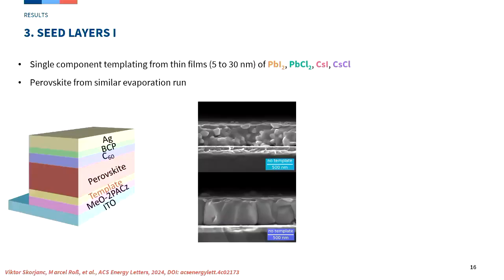So you have grains that go from all the way the bottom to the top, and they are large and homogeneous. This is how it should be. Within the same run, you don't do anything differently than placing samples at different places in the chamber, yet you see small grains and a very different morphology. So this is how bad it is.